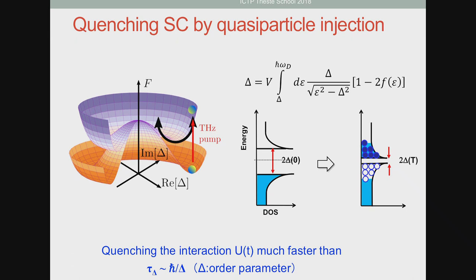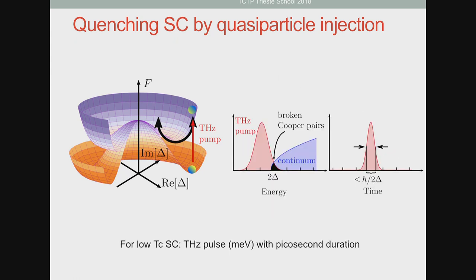One way of seeing how you can quench your superconducting gap using terahertz light or infrared light near the gap frequency is by looking at the gap equation. If you modify the temperature, if you create quasi-particles out of equilibrium, according to the gap equation this is going to change your gap amplitude, and this could provide a way of quenching your superconducting system. So essentially you create particle-hole excitations, Bogoliubov excitations, in a non-adiabatic way. But for that there is a condition: the width of the optical pulse has to be shorter than h bar over delta. This can be done, for example, by shining light that is below the gap, with an energy slightly below 2 delta, but a width in time that is shorter than h bar over 2 delta.